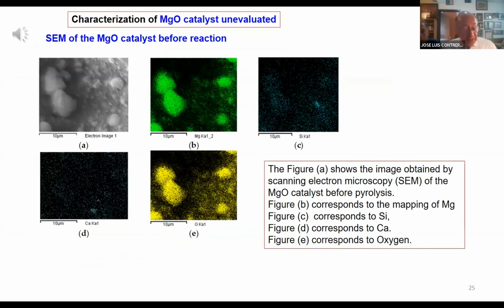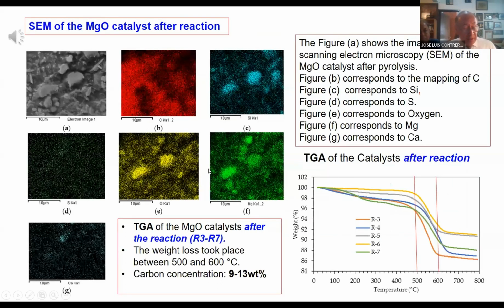In this slide, you can see the observation by scanning electron microscopy of the unevaluated magnesium oxide catalyst, which shows the following elements: magnesium, oxygen, silicon, and calcium. This is an electronic map. The observation by scanning electron microscopy of the tested magnesium oxide catalyst shows the following elements: carbon, silicon, sulfur, magnesium, oxygen, and calcium.